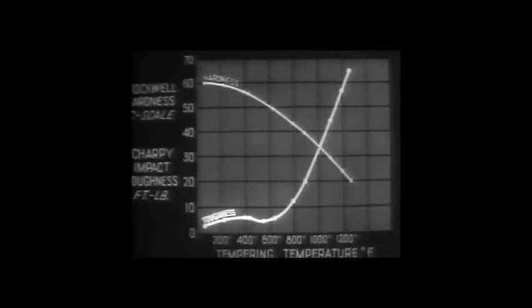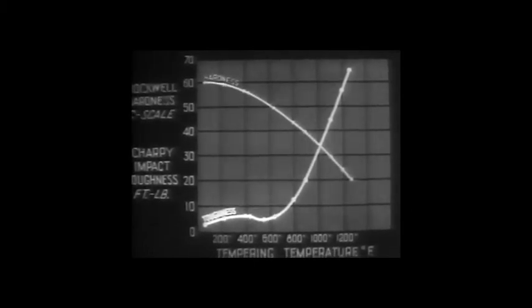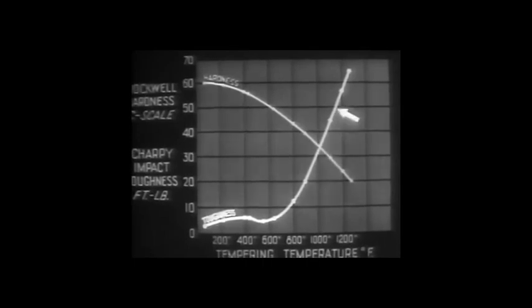We can see that there is a generally consistent relationship whereby hardness decreases as toughness increases. But there is an exception to this rule. Between 450 and 650 degrees, toughness actually decreases a little. However, there is no corresponding deflection in the hardness curve. This is called the brittle tempering range. But at temperatures above this range, and particularly beyond 800 degrees, the toughness increases very markedly. The same graph, drawn for any other plain carbon steel, would show a similar relationship between toughness and hardness.